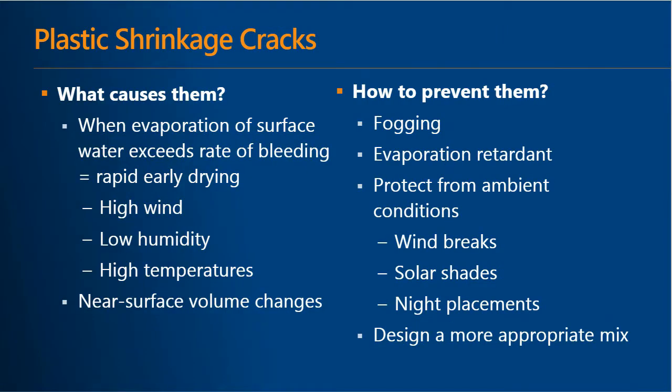So plastic shrinkage cracks are called plastic shrinkage cracks because the concrete paste is still in its plastic form, so it is not yet set. And so when you get evaporation of surface water from the exposed surface of your element, that exceeds the rate of bleeding, you're losing moisture from your exposed surface and you're not replenishing that moisture at the same rate that it's being lost. You'll get a drying of that top surface, and that will result in a near surface volume change. And that volumetric change is what actually results in the cracking.